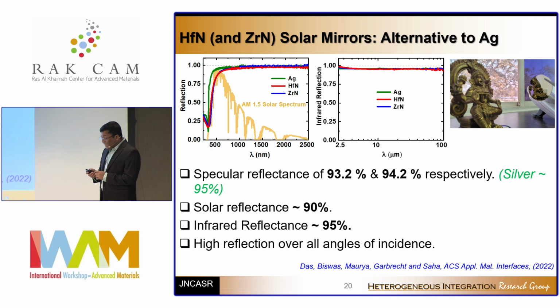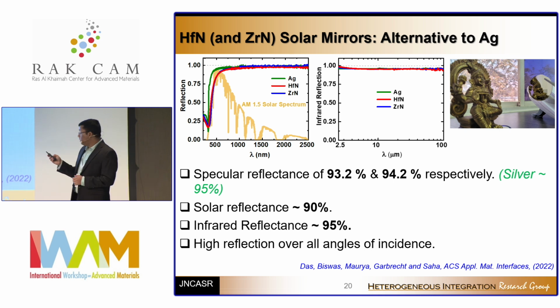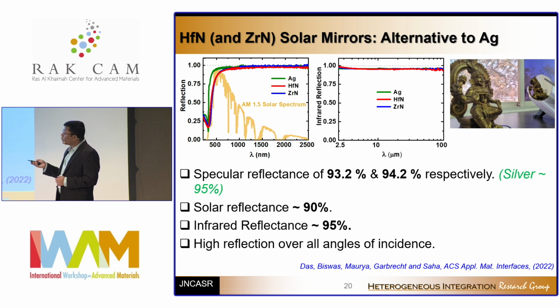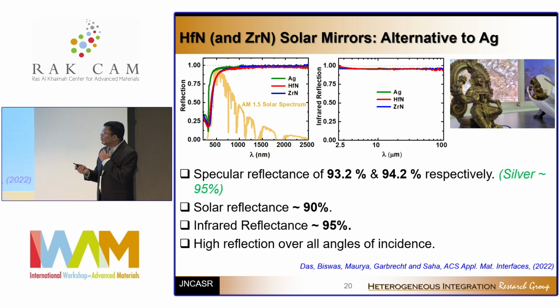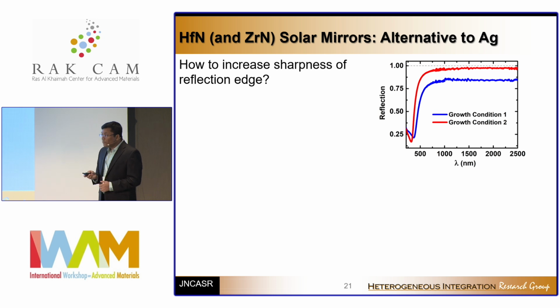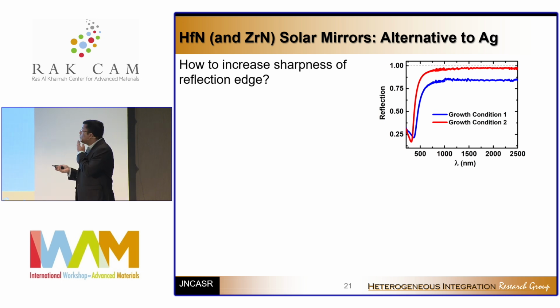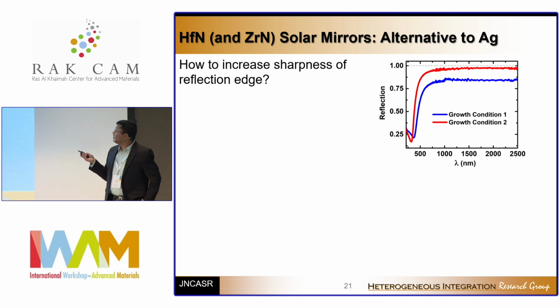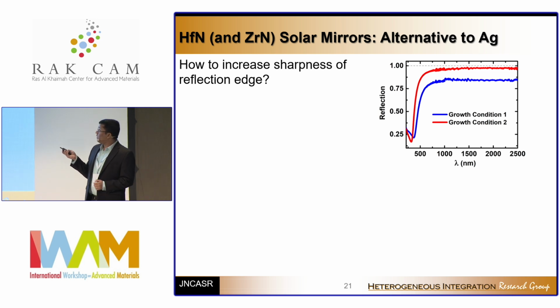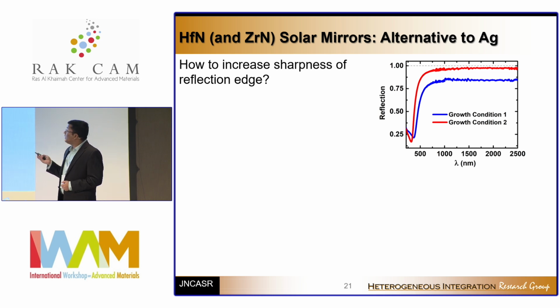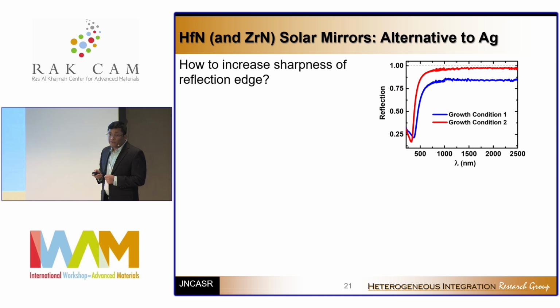Now, initially we were not sure that we would be able to make such a good solar reflector, because although you can make the plasma frequency at a particular wavelength by doping a certain range of carrier concentration, unless you can keep the reflection edge extremely sharp, you can still end up not having a good reflector. And that is why it's extremely important to increase the sharpness of the reflection.